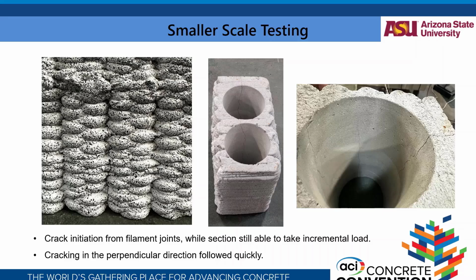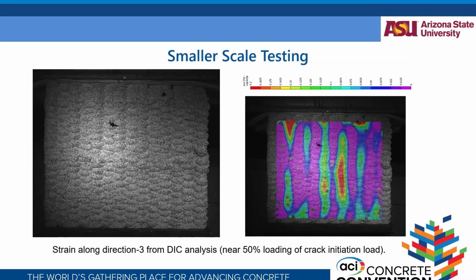The strength for this mix was 48 MPa in this direction of test, but when we tested this section, the strength was in the range of 20 MPa, most probably due to multiple factors. The cubes were perfectly cut into cubical shapes, so there were interlayer joints, but there were no stress concentration points like this on the cubes. Second, we cored cylinders out of it, so there could be significant damage due to the coring process that we used. We are in the process of doing more structural testing on the infills, which we have not done yet, but we are trying to do similarly.